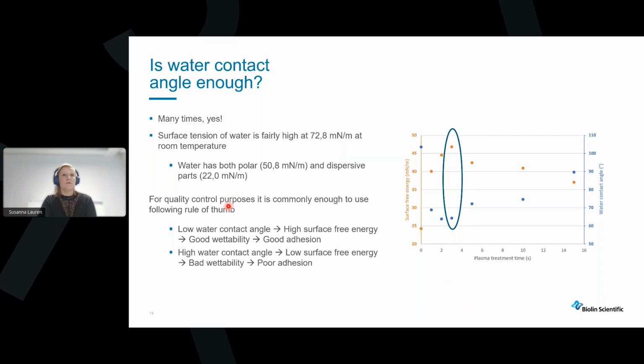And also, if we think about quality control purposes, we can think of it so that a low water contact angle means high surface free energy, good wettability, and good adhesion. And vice versa, of course, if we have a very high water contact angle, then we have low surface free energy, bad wettability, and poor adhesion.